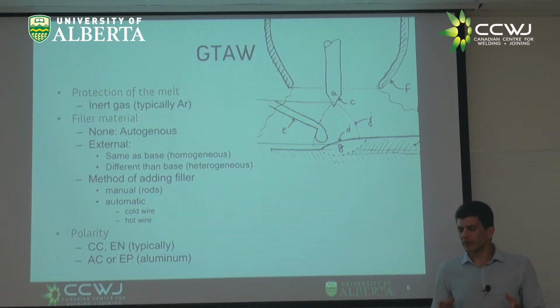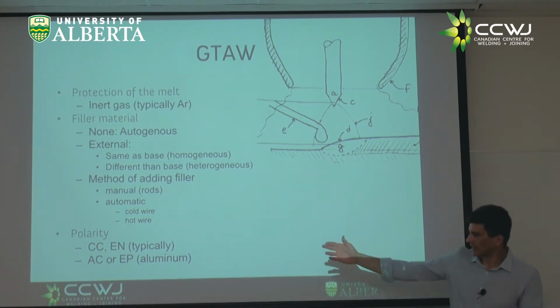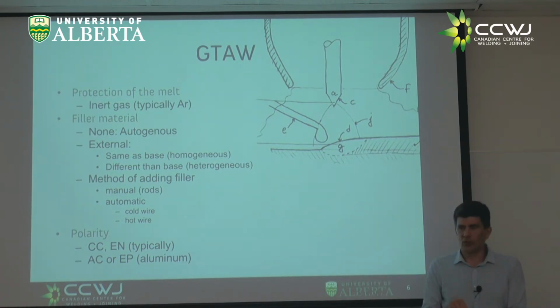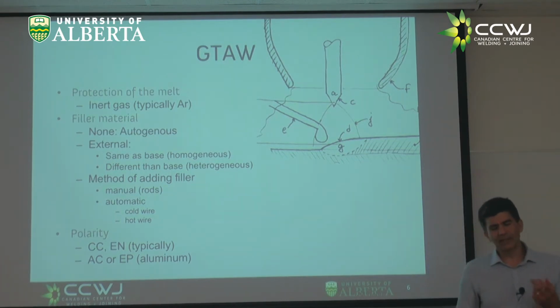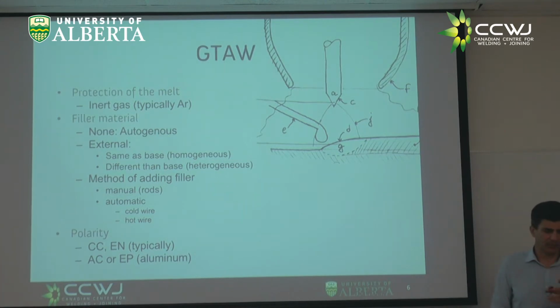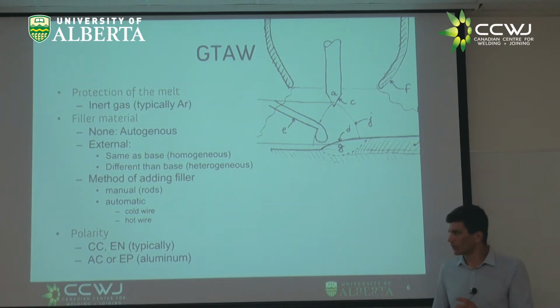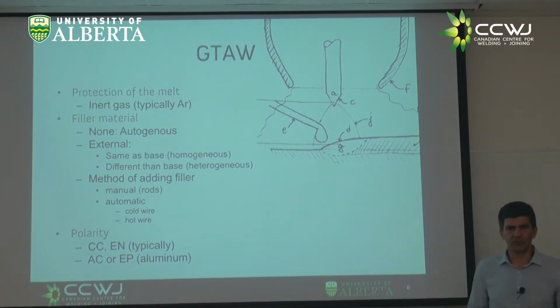For reasons people don't really understand, when the electrode is positive, the plate is negative, and that breaks the oxide layer. Nobody knows exactly why. But you have what is called a cleaning effect in aluminum. In steel, you don't really need that, because steel doesn't have this really strong oxide layer on top, right? So you have different levels of AC, and different levels of cleaning of the aluminum. You're going to see that difference between steel TIG welding and aluminum TIG welding. And as I talk about polarity, I'm leaving aside many details about the physics of plasmas, which we will discuss. For now, you have to take me on faith about these polarities.